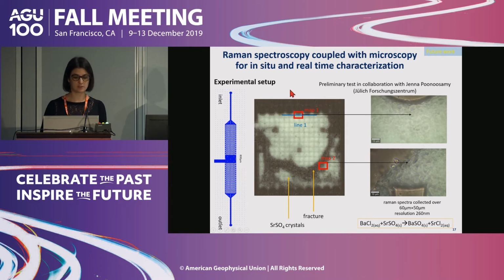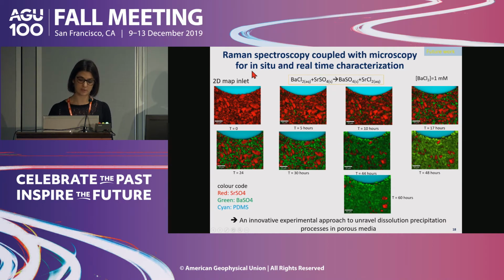And what is new in this work is that we use Raman spectroscopy that is coupled with microscopy to have really an in situ characterization of the different minerals that are present in the system. These are some of the preliminary results that we get. So we are really able, during the reaction, to follow the different minerals. In red you have the strontium sulfate, in green you have the barium sulfate, and with time you see that the strontium sulfate dissolves and we have precipitation of barium sulfate. This is one example of a 2D map that we can get from these experiments. We can also get 3D reconstruction of the minerals. We are now processing the images.